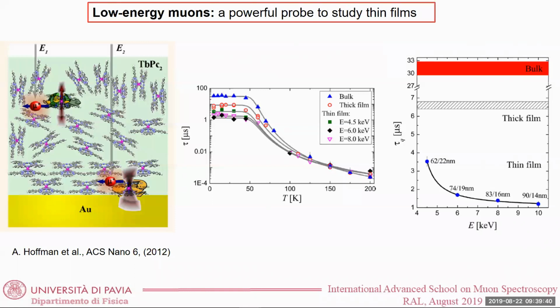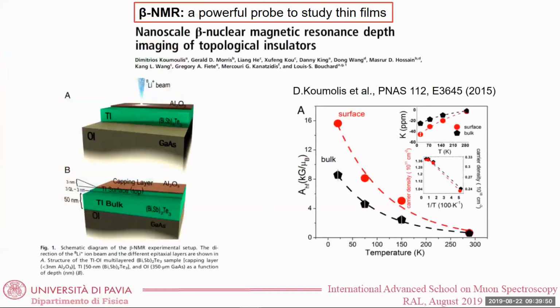Of course, you can use this type of technique very similarly also in the case of beta NMR. Indeed, beta NMR is a technique where the nuclei implanted in your system penetrate just a few nanometers, and so it can be useful to study, for example, topological insulators. In this respect, it is very similar to low energy muons. You can study the difference in a topological insulator between surface and bulk, and so distinguish the metallic and insulating behavior. But again, keep in mind that the muon is a much smaller perturbation with respect to the lithium ions which are put inside.